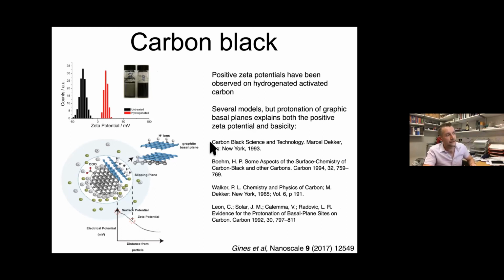But the thing is that literature has been seeing positive zeta potentials for 30, 40 years, right? And we know that we have sp2 on the surface of the diamond particles, so why not, right? So I took, in Germany, I took some carbon black and hydrogenated it, and of course you see a positive zeta potential. You only do this once, so it's very messy, it gets everywhere.